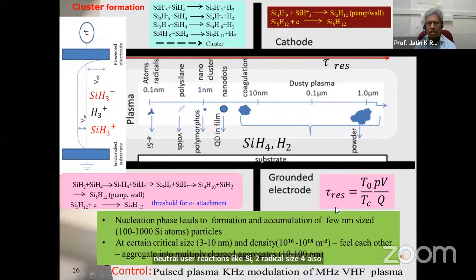So what happens depends on the residence time of the gas in the chamber. Residence time depends on the pressure, the volume of my plasma zone, and the flow rate of the gas. If you keep increasing the residence time, either by pressure or by volume, it will go from simple radical formation to making amorphous silicon. Then clusters are formed, they go inside and make polysilane, and voids appear inside. If they get slightly bigger, they become small nanoclusters that get into the material. It's called polymorphous material. Or still bigger than that, maybe 1 to 4 nanometers in size,